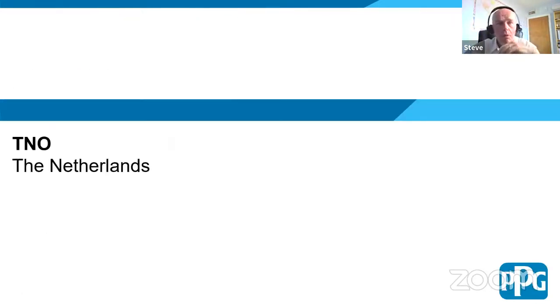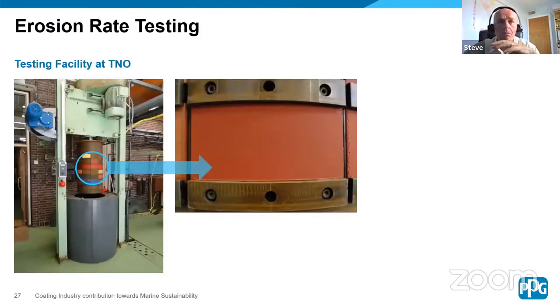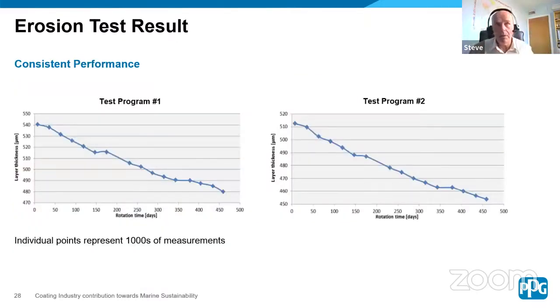TNO, another very well-known institute in the Netherlands, a similar appearance, but a different way of looking at the performance of the coating. Here they're looking at the polishing, or as they describe it, the erosion rate. And what you have here is test run one and test run two, almost showing perfectly linear delivery over a year and a half measurement period. Now, each individual point that you see on these graphs represents thousands of readings, but you can see that they're almost identical. They almost overlap each other perfectly, which is very, very encouraging because that means you get consistent delivery of fresh biocide to the surface in a timely manner.